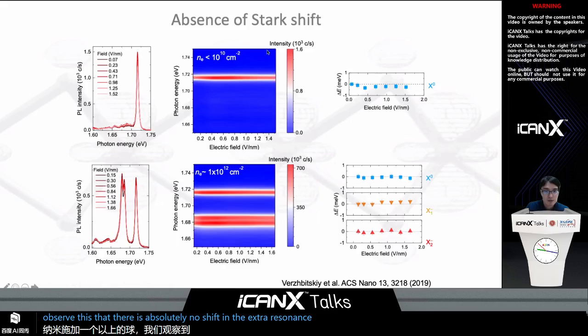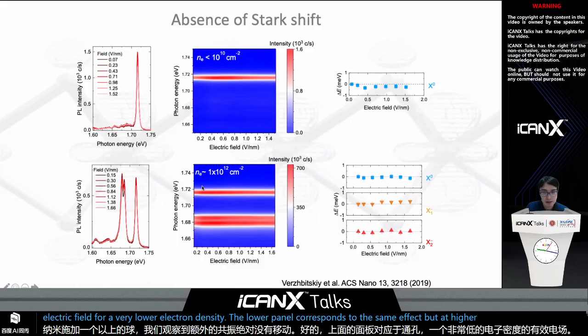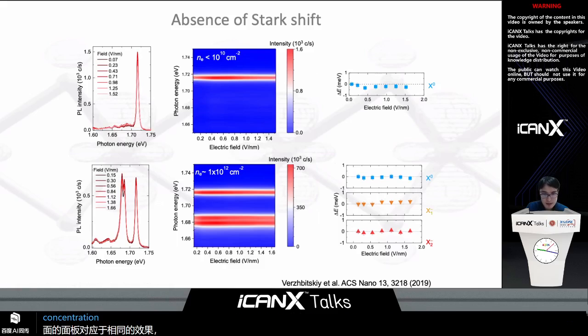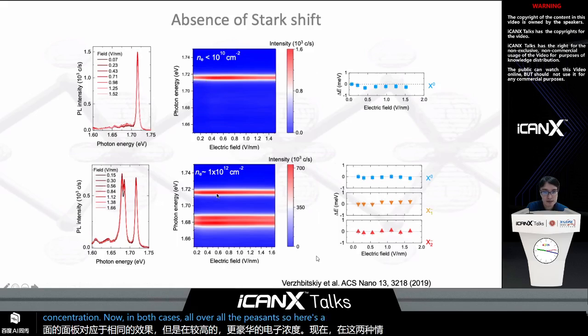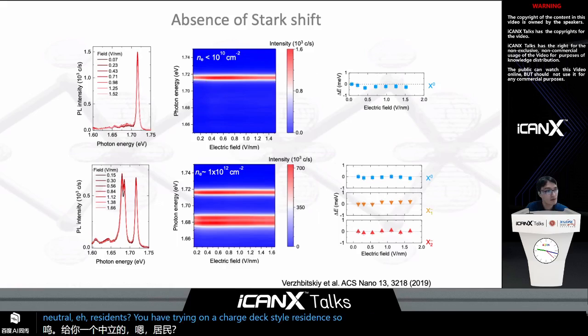Okay, the upper panels correspond to the effect of electric field at very low electron density. The lower panel corresponds to the same effect, but at higher, greater electron concentration. Now, in both cases, all the resonances, so here's a neutral exciton resonance, and on top of the neutral exciton resonance you have the trion, the charged exciton resonance. But all of these states don't shift with electric field, despite this extremely high electric field.